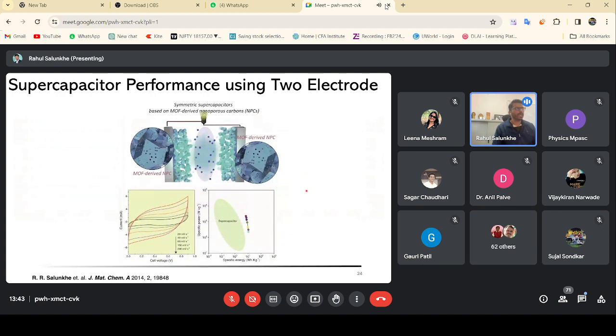So this is the typical characteristic, and now we have used this kind of carbon in the two electrode configuration in the aqueous electrolyte like H2SO4, and we can see that on one side we have MOF derived nanoporous carbon, on the other side also MOF derived nanoporous carbon. With an H2SO4 electrolyte we can get the CV shape up to 0.9 volt maximum, because there is a limitation of the potential window. They can have very limited specific energy and specific power.